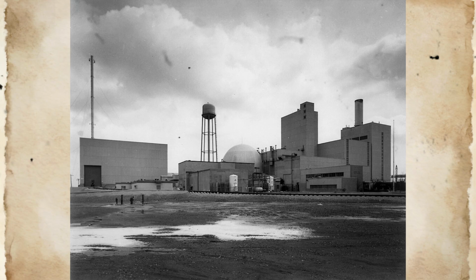Examination of the damaged fuel assemblies provided detailed confirmation of the thermal progression that had led to fuel melting and fission product release. Metallurgical analysis revealed that peak fuel temperatures had reached approximately 1,500 degrees Celsius in localized regions, well above the melting point of metallic uranium fuel. Post-irradiation examination showed evidence of fuel melting, cladding oxidation, and structural distortion consistent with severe thermal transients under reduced coolant flow conditions. Cladding examination revealed oxidation patterns and mechanical failure modes characteristic of high-temperature exposure and thermal stress.